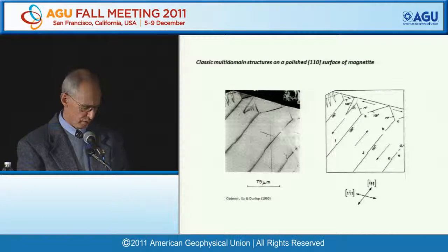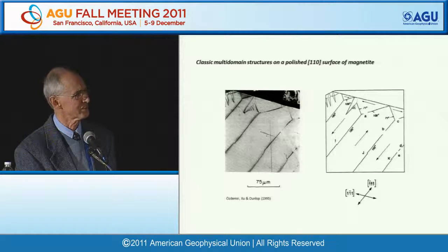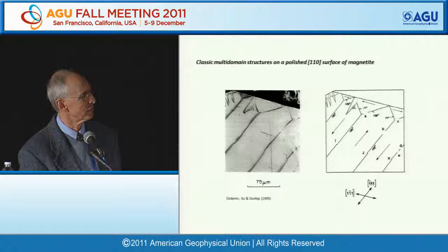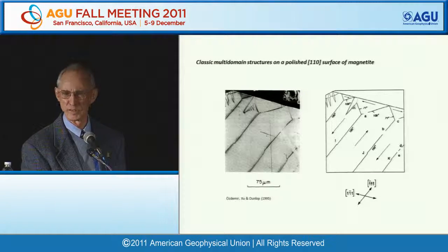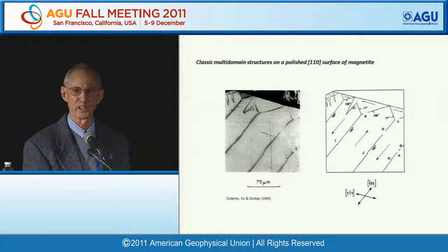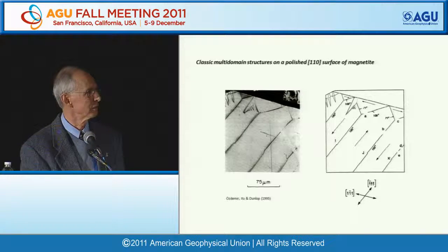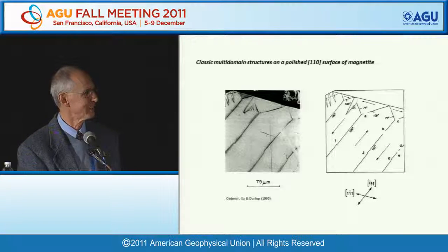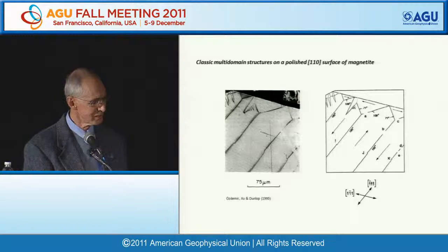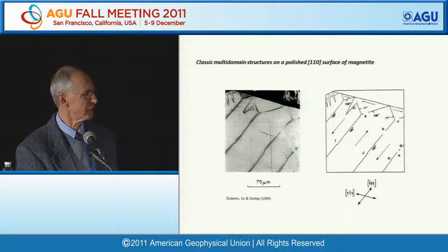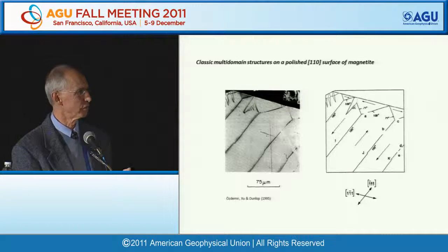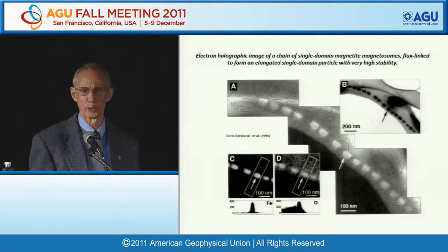Well, if you go looking for classic domain structures by polishing very carefully a 110 surface of magnetite, and Özdemir does this magnificently, which is why these pictures here are better than anything you can find in a textbook on domain structures. These show not just spike domains, reverse spike domains, they show spikes upon the spike domains. They show perfectly developed 71 and 109 degree walls, and also lovely 180 degree walls between the body domains. Everything is there, just as Landau and Lifshitz showed in their paper.